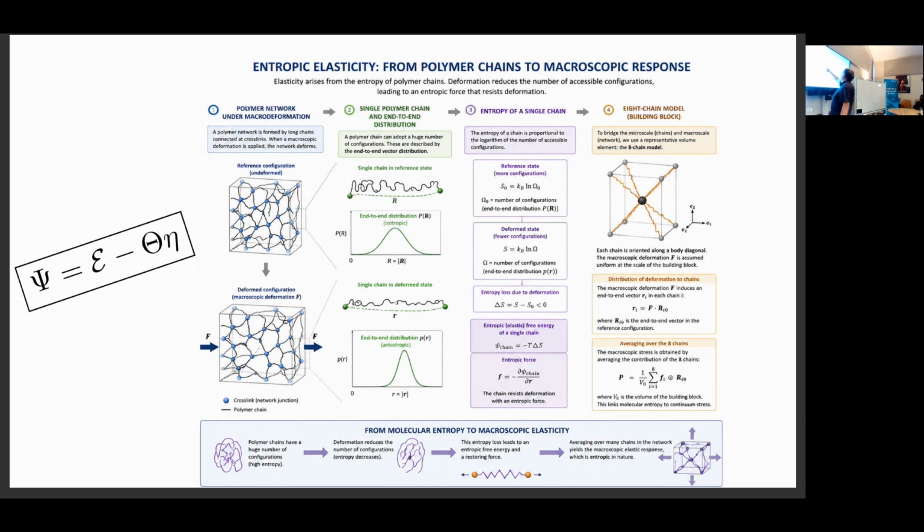And how can you go from this mesoscopic structure to a macroscopic model? First of all, you have to have the model of a single chain, okay? You have to say what a single chain is and why there is a reference length for the single chain. There is a reference length just because it's highly probable among all the possible lengths. And if I start to stretch, I need forces because it's less probable. Indeed, if you stretch the chain to the maximum, there is only one configuration that can satisfy that, and then I need a lot of force, an infinite force. Remember that, an infinite force.